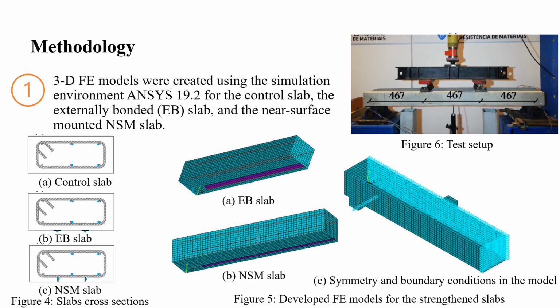Three-dimensional finite element models were created using the simulation environment ANSYS version 19.2. The geometrical configuration and material properties are the same as the ones tested by Azevedo et al. in a previous experimental investigation, where they tested a control slab, an externally bonded slab, and a near-surface mounted slab